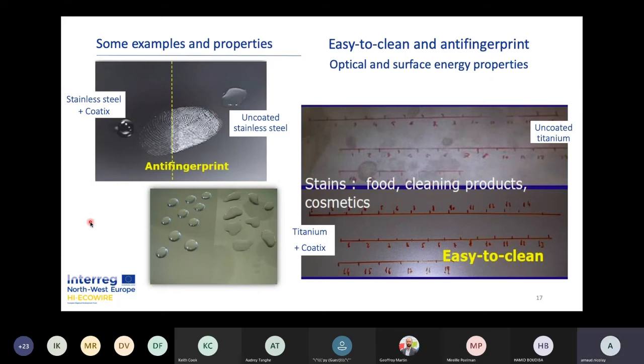So Coatix can be used as an anti-fouling, anti-dirtying coating. First of all, it has easy to clean and anti-fingerprint properties, thanks to its low surface energy. Coatix reduces the visibility of the fingerprint on stainless steel, for example, and it facilitates the cleaning with a simple wipe of a cloth. It's also easy to clean for food, cosmetic, or other stains, as can be seen on these titanium samples.